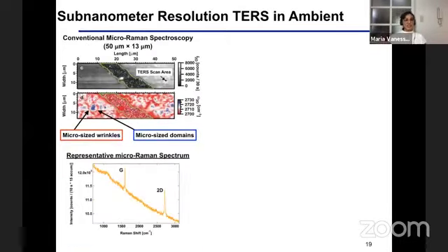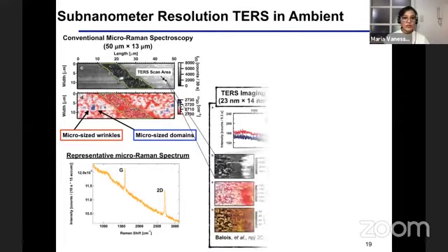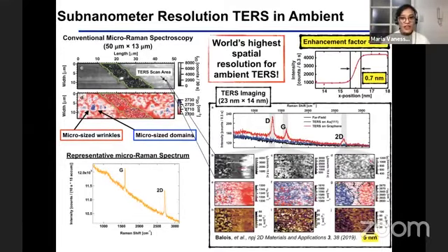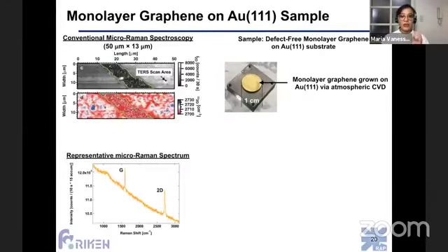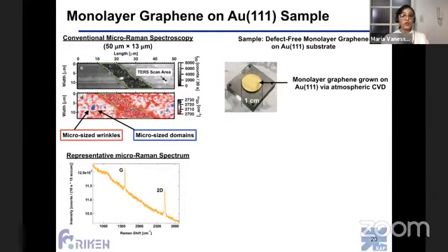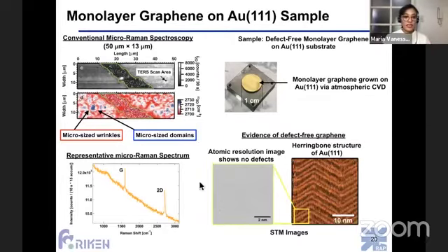The beauty of the STM is that you can control very well the tip sample distance, which means that the stability is very nice. Using this system, we were able to get a very high spatial resolution of 0.7 nanometers. This is currently the world's highest spatial resolution for ambient TERS. The sample that we studied is simply a gold 111 substrate with a monolayer graphene, which is pristine, wherein there are no defects. We scanned a large area here of 50 microns by 13 microns, but the actual scanned area is just this small area over here.